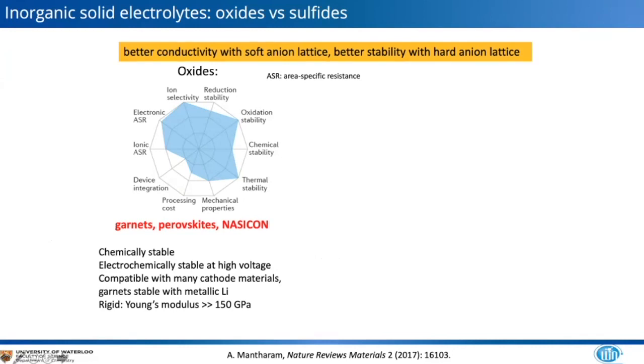So I won't be talking about polymer electrolytes today, not because they aren't a viable technology. They tend to have conductivities that are a little lower than what are desirable, but we work on the solid inorganic electrolytes. This is just a comparison between oxides and sulfides. And as you might imagine, one obtains better conductivity with a soft anion lattice, such as a sulfide, but better stability with a hard anion lattice.